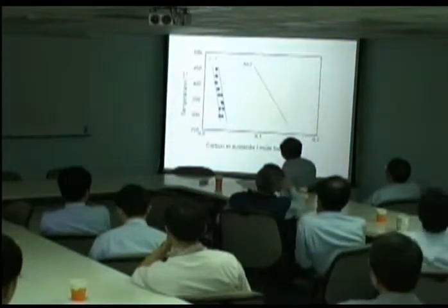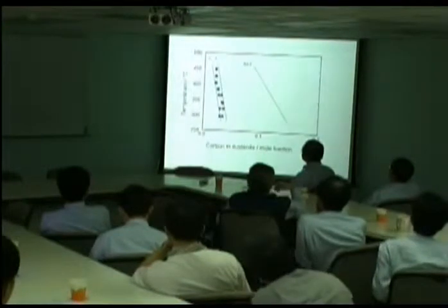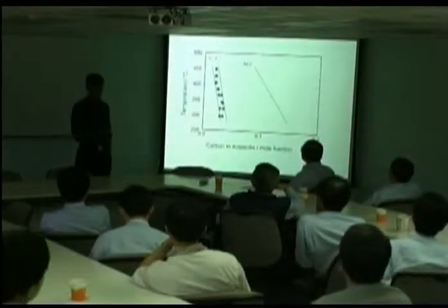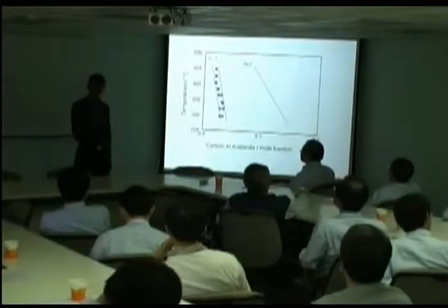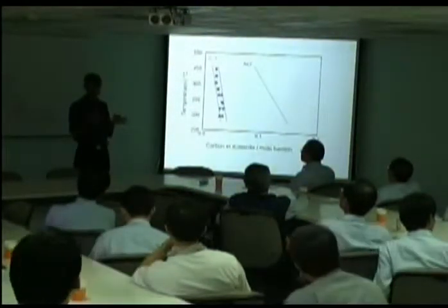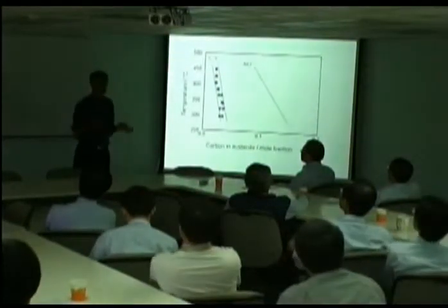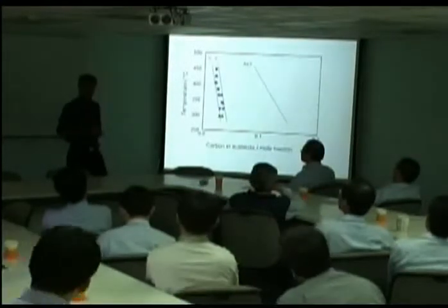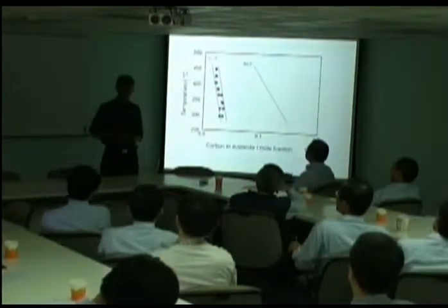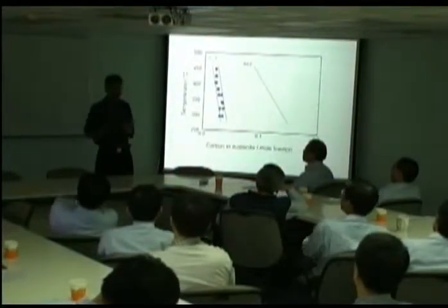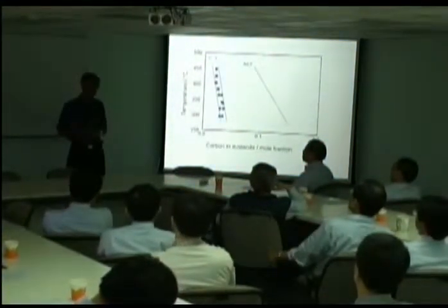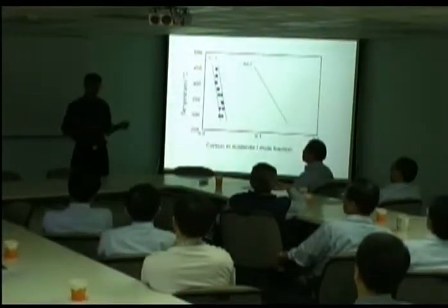So look, this is just one of many, many experimental results which show that the transformation stops a long way before equilibrium is reached in the austenite. So we can conclude that even though when we make an observation, the carbon is in the austenite, not in the ferrite, during growth, the bainite grows just like martensite without any diffusion of carbon. Once we accept that, there are many other predictions you can make, all of which can be experimentally verified. So let us accept that bainite forms without any diffusion. Well, the first thing is that if we measure the growth rate, it should be much, much faster than allowed by carbon diffusion, because the diffusion happens after growth.